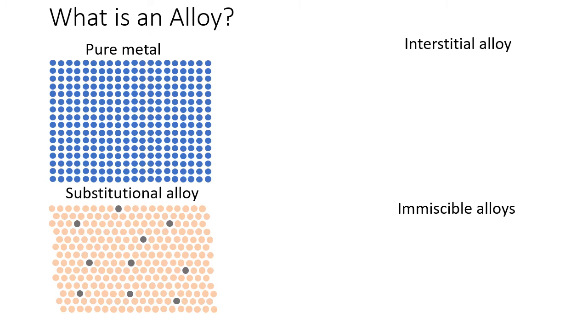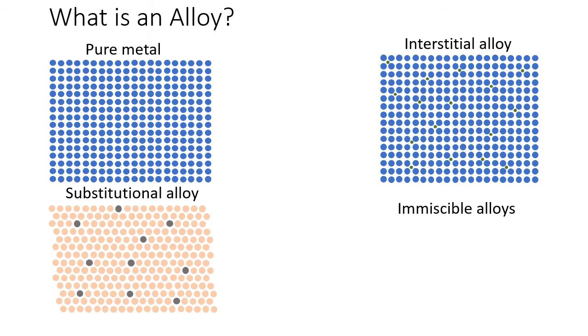First, we can get substitutional alloys, which is where atoms can be switched out without significantly affecting the crystal structure. A common substitutional alloy is bronze, where the hexagonal pattern of the copper atoms is not changed by the addition of tin atoms. Another type of alloy is the interstitial alloy, where atoms from a smaller element sit in the spaces between the larger metal atoms in the crystal. An example of this would be steel, where the iron atoms continue to form a cubic structure and the carbon fits in the gaps in the crystal.